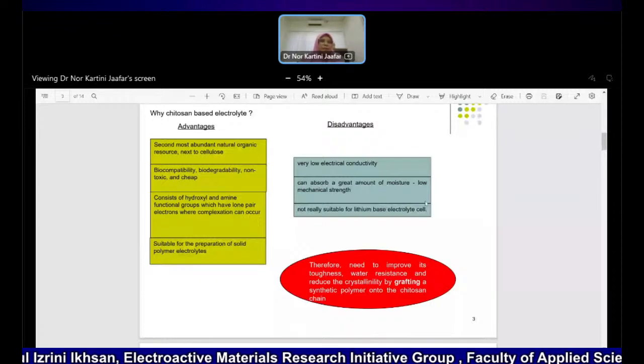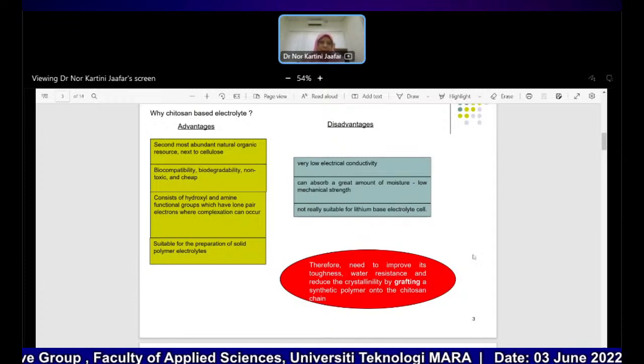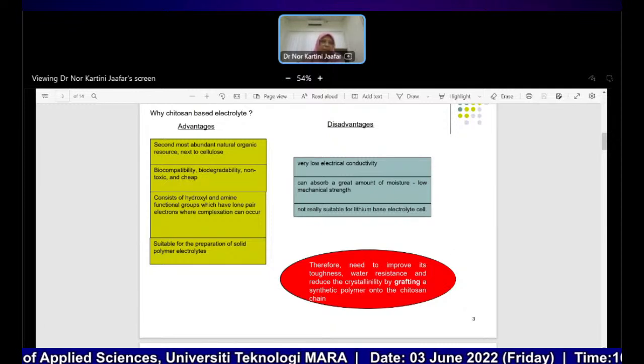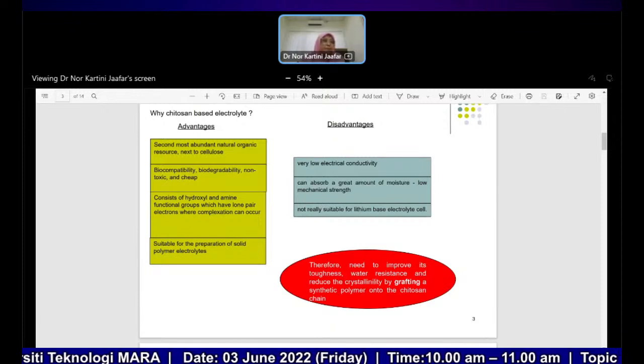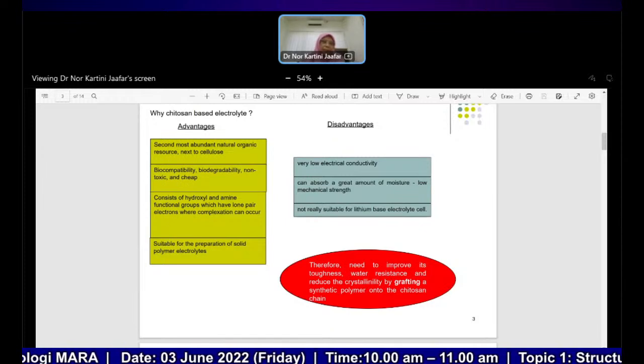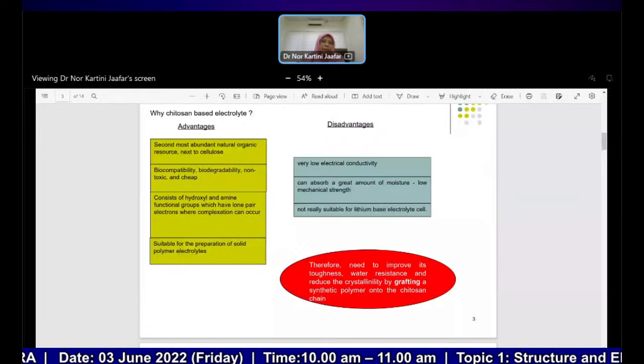And the nature of Chitosan is that it tends to absorb moisture. When it absorbs moisture, the mechanical strength of the structure becomes low, and when water is involved, it's not very suitable for lithium-based electrolyte cells. So I tried to improve the toughness of Chitosan and its water resistance, and tried to enhance the conductivity of Chitosan by grafting a little bit of synthetic polymer onto the Chitosan chain.